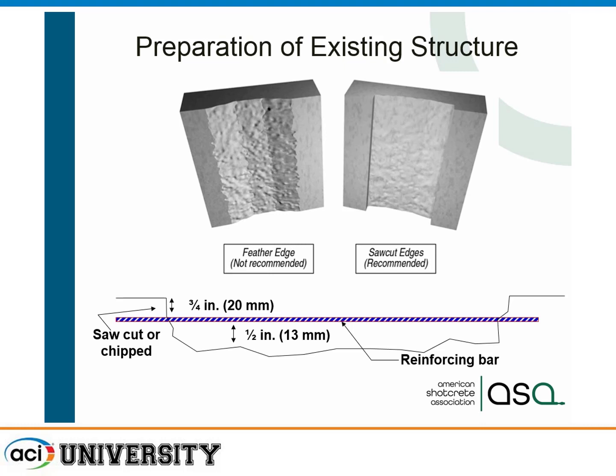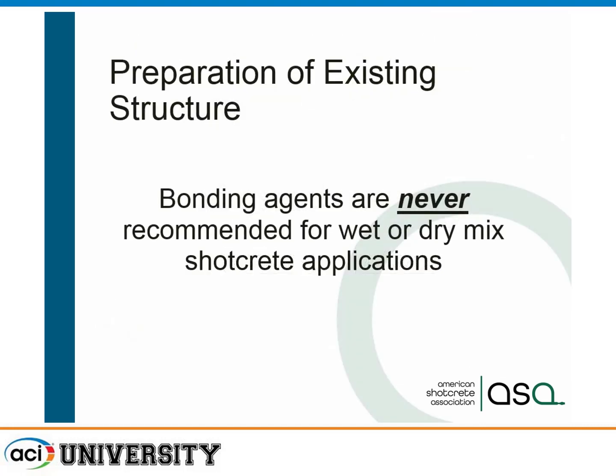Many of these are saw cut, but we don't want to shoot against the saw cut. So we like to have that surface sandblasted or roughened at least so that we can get good bond of our shotcrete during placement. We never recommend bonding agents. I get a lot of calls from inspectors or contractors saying the inspector told me I had to use a bonding agent. Well, a bonding agent's fine when you're casting concrete, but remember, we have a very active process.